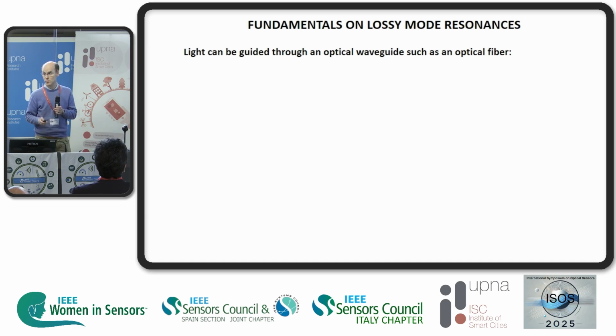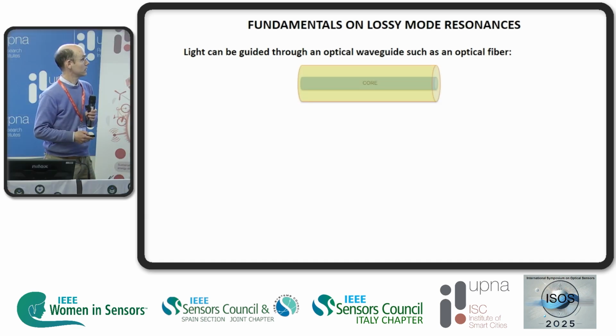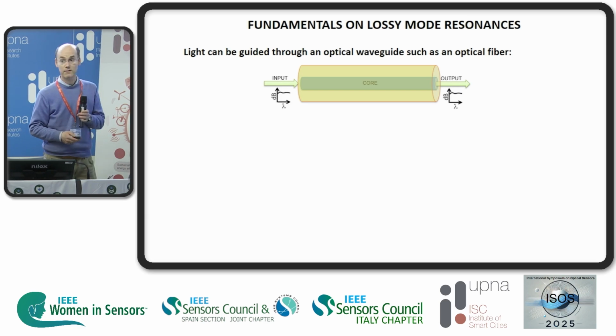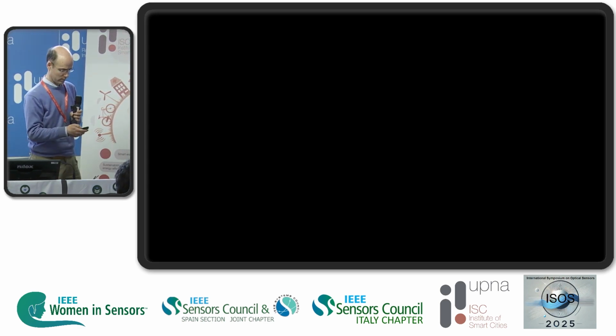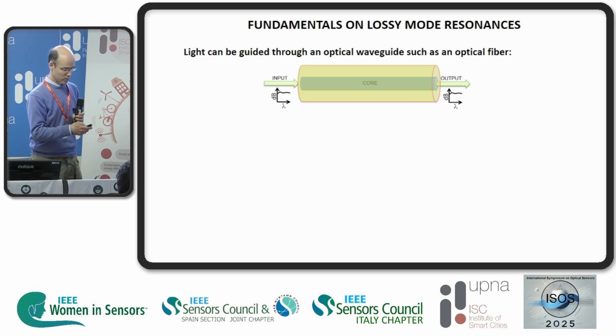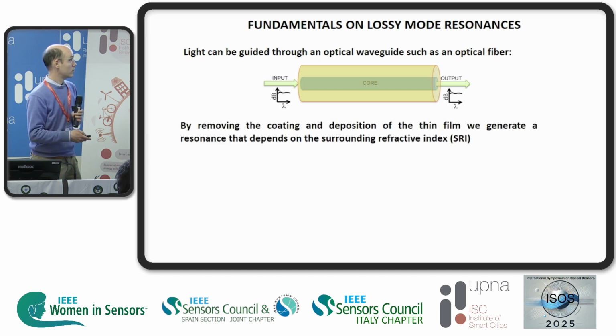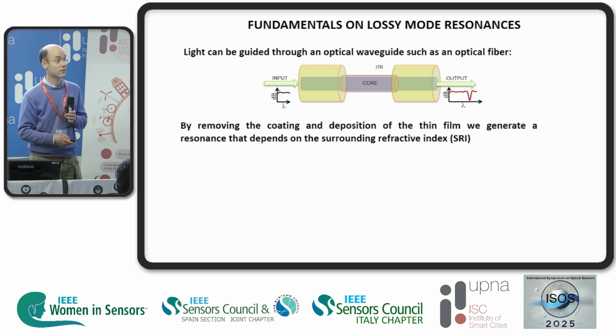Light can be guided through an optical fiber like this one. If we don't modify the fiber, the transmission spectrum here is similar to the transmission spectrum we get in the output. By removing the coating and depositing a thin film, we generate a resonance in the output, as you can see here, that depends on the surrounding refractive index and the thin film thickness.